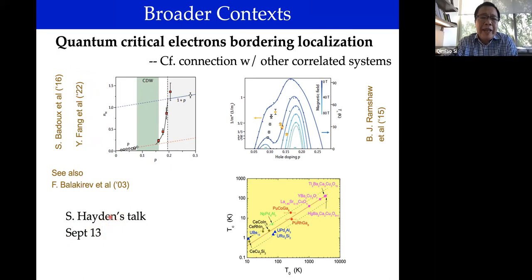That we heard from a very nice talk by Stephen Hayden two weeks ago in this series. And also in YBCO, there's a quantum oscillation measurement showing the tendency of the mass, which is divergent, which the quantum oscillation measurements in CeRhIn5 that I mentioned also provide evidence for, the cyclotron mass showing the tendency for divergence. So while in the general sense, whether the Hall effect really provides a phase diagram like this with small to large Fermi surface change, I think that it's still an ongoing debate in the cuprate context.